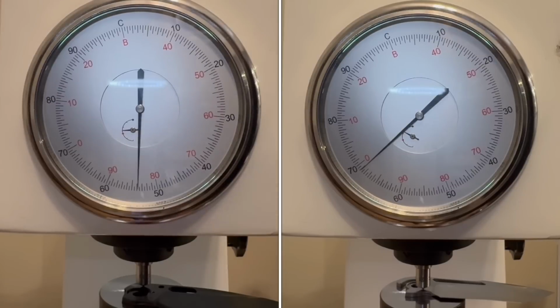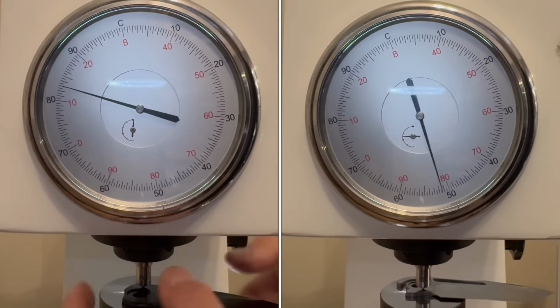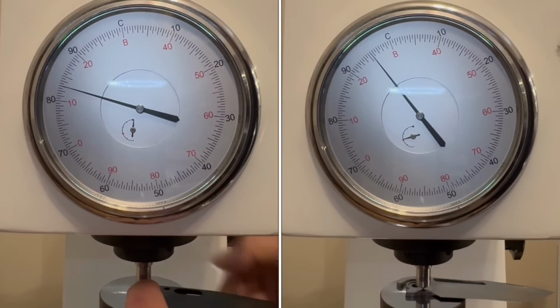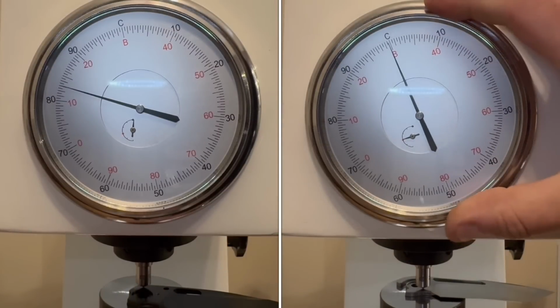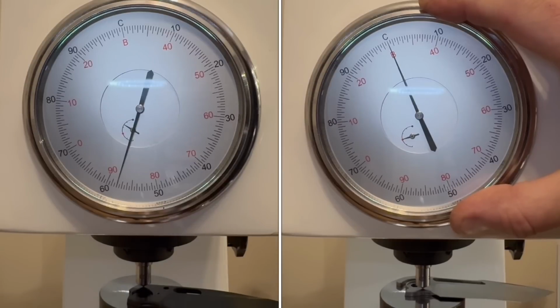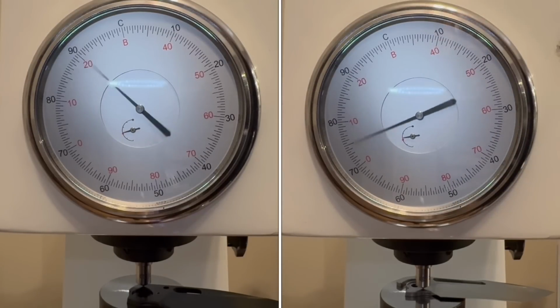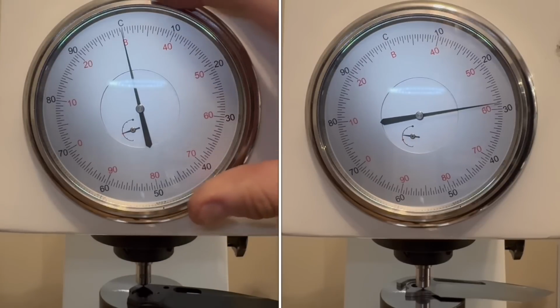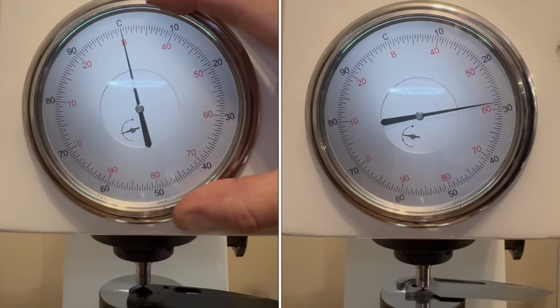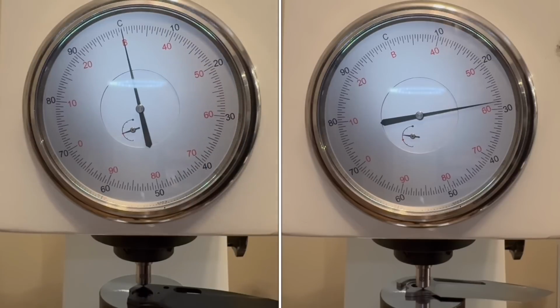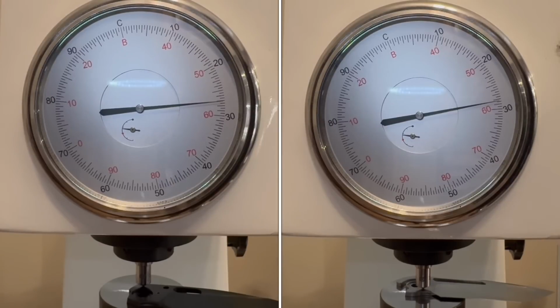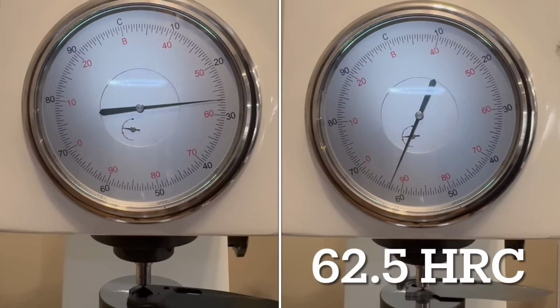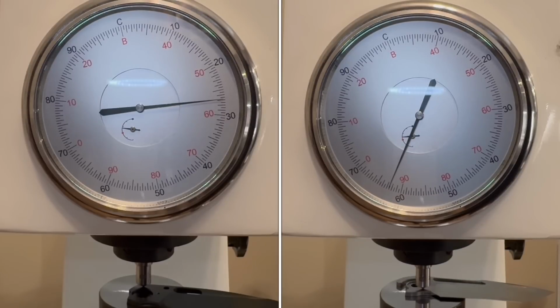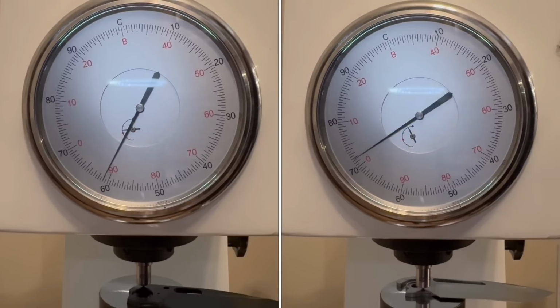Okay, let's set up on the right to test the Offender again. Setting up the 0 here on the right. And we're going to do the same on the left as well. So it's confusing to me. Maybe you'll have to watch it a couple of times and just look at the left or at the right. Especially these pauses when the major force is applied for 12 seconds drive me nuts. But here you go. So we're about ready to release the major force on the Offender. And we got 62.5 HRC. And time to check on the Excalibur on the left.